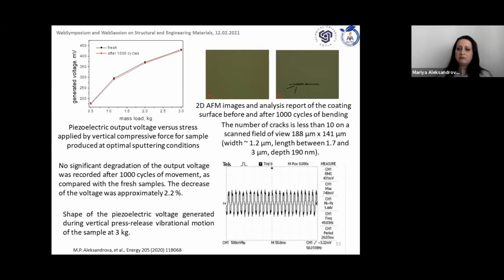And two-dimensional AFM image analysis showed that the microcracks appearing are fewer than 10 for a scanned field of 188 by 141 micrometers, and the depth is 190 nanometers, which, considering the total thickness of the film, is not really a great depth. So the films are really stable, and here is the electrical signal that could be extracted when you mass load the samples at 3 kilograms. The signal is clear, without any spikes, with great periodicity.